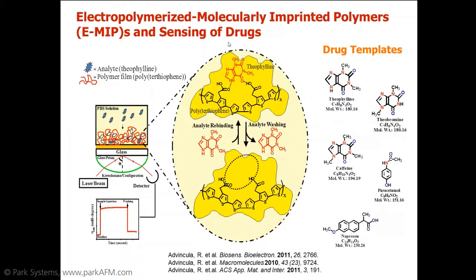Okay, here I'm showing you some of the drugs that we first investigated using this approach. The monomer we utilize in this picture is basically a thiophene monomer, which is capable of hydrogen bonding with theophylline. In this case, we can do theophylline, theobromine, caffeine, paracetamol. So you can imagine that each of these analytes can be specifically made as a molecularly imprinted polymer film on top of this gold electrode.